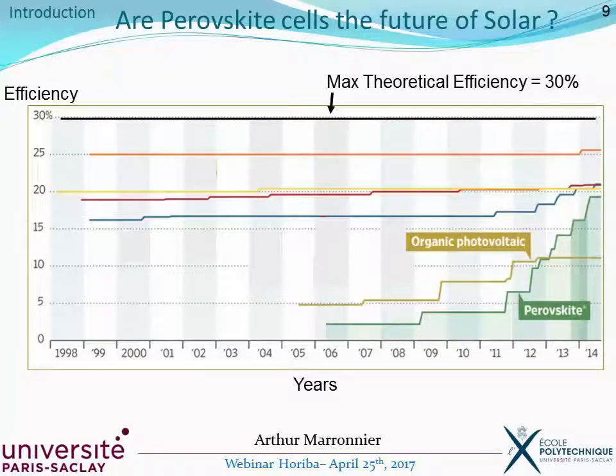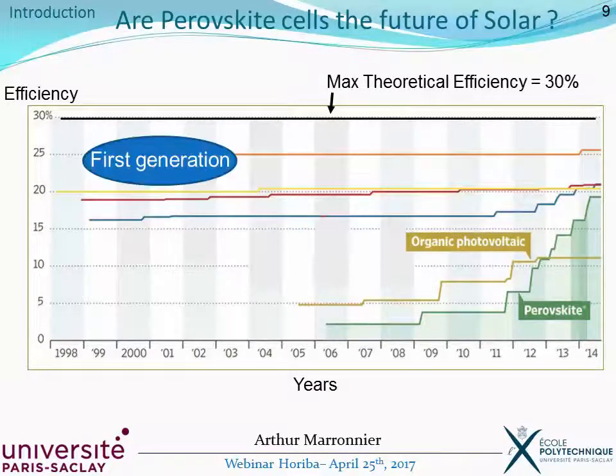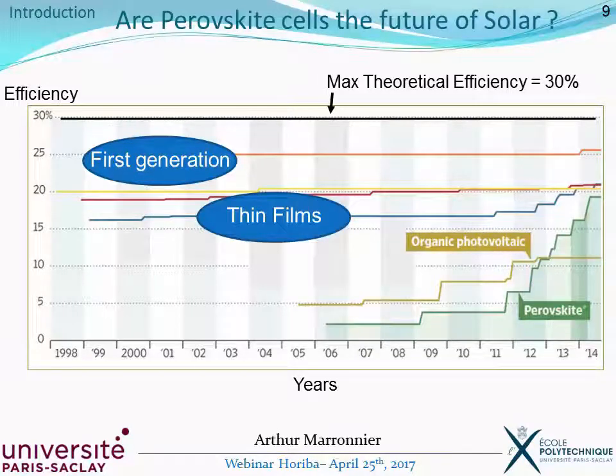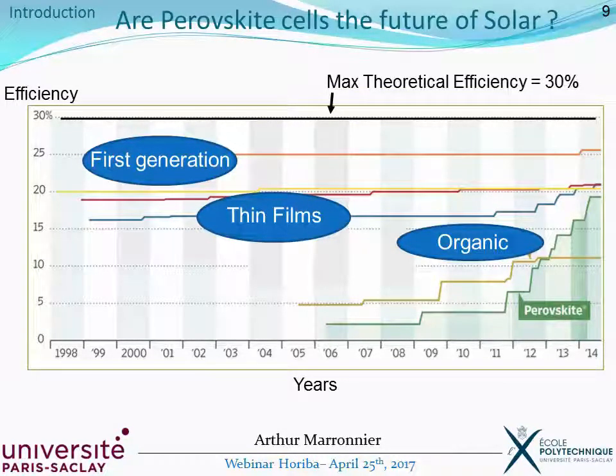In terms of efficiency, here on this chart, you see the evolution of the different generations versus time. First, the first generation has already reached this very nice 20-25% efficiency, very close to the maximum theoretical efficiency. And it took 30 years of effort to this generation and then to the one of thin films to reach these high values. Then you have the organic photovoltaics, which, as you can see, has reached a plateau around 10% and is not improving anymore. But last, you see this new generation of perovskite solar cells that have jumped in only a few years from 4% to around 20% efficiency.